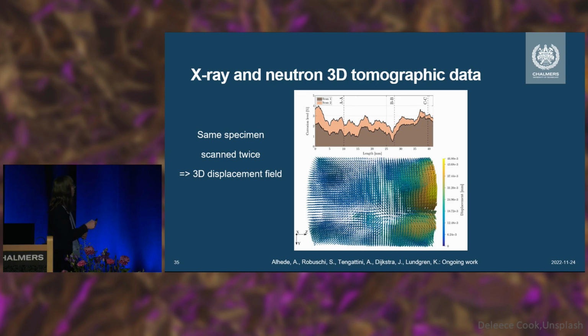What you can see here on the y-axis is the corrosion level, and on the x-axis is the length along the specimen. The dark brown was actually corroded already the first time we scanned it, so that's the corrosion level from the first part. And the light one is after the night, after subsequent corrosion. And we can see how it varies along the length. And what we managed, and I should say that this was really not super easy to manage, Andreas really struggled before he could solve this, but he could manage to actually follow each pixel with digital volume correlation so that we can get the whole displacement field.